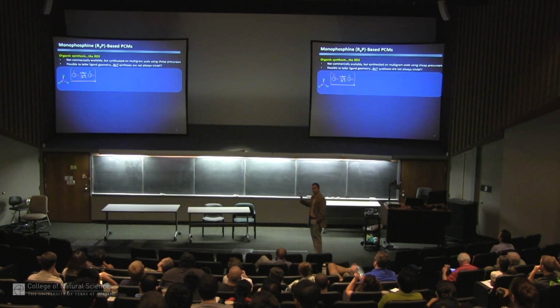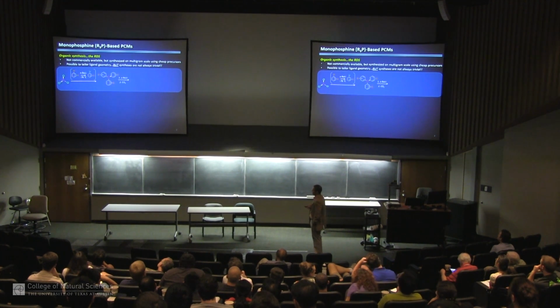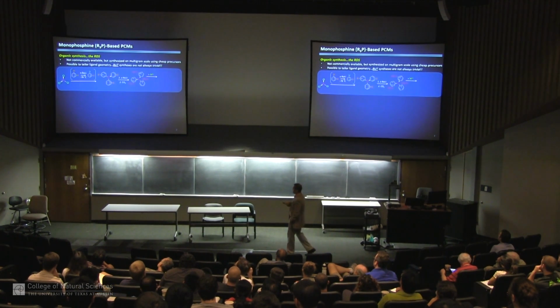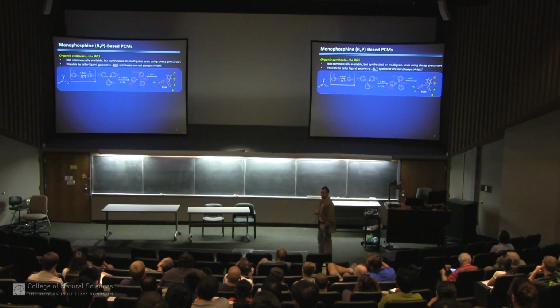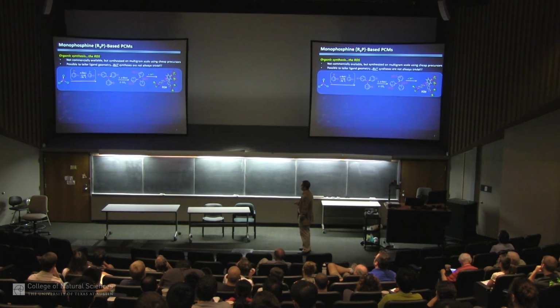I'm not going to go through much organic chemistry, just to show you one slide that proves this is modular and that we can take this chemistry as far out as we want. We do the chemistry to make these ligands by simple lithiation of cheap reagents. And this is important because if you want to scale these up, obviously the precursors have got to be fairly cheap and readily available. This gets us to these intermediate phosphines that have, for example, bromo groups wherever we want them. We can lithiate those again, turn them into acids. Then finally we take this ligand and react to make a polymer. And then we can do the crystallography and we can start to do some chemistry with the material.